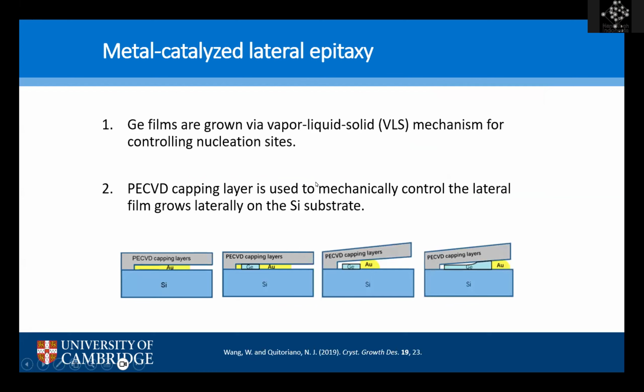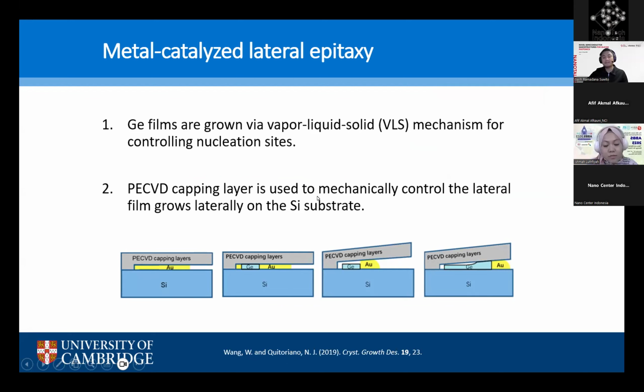Okay, so to get rid of those limitations associated with the conventional heteroepitaxy techniques, we have come up with a novel technique called metal catalyzed lateral epitaxy. Our technique relies on two important building blocks. First, we use what's called the vapor liquid solid or VLS process to control the nucleation site of germanium crystal for the case of germanium on silicon. And the growth process is under what's called a microcrucible structure. So we make use of a mechanical capping layer inside the microcrucible structure to mechanically confine the growth, creating a template for lateral epitaxy.